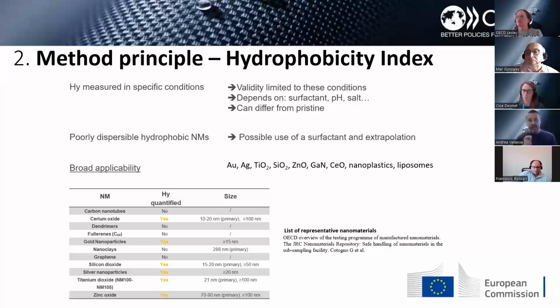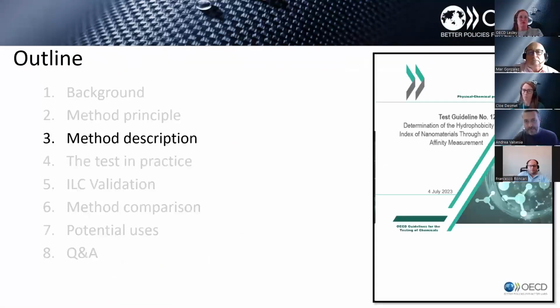This is basically due to the limitation of the dark field microscopy detection, so we are not able to detect, for example, carbon nanotubes, fullerenes or graphene. But there are alternative techniques to measure the affinity of these materials to our collectors, and if you are interested, at the end of the presentation I can explain what the alternatives to dark field detection are.